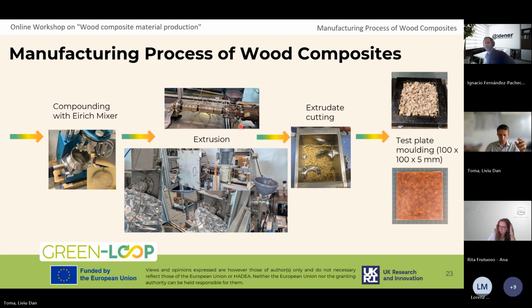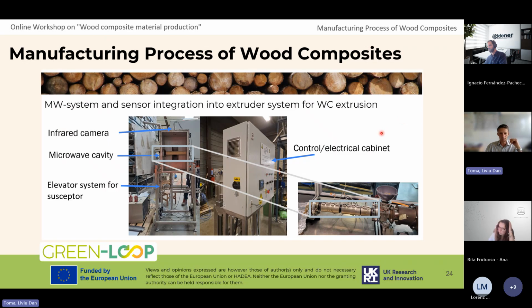The mixtures obtained through the extrusion process were cut, and then with press molding we got test samples in the form of plates, and these were further characterized and machined for special samples for the tribological characterization. As I said, a big part of the work was done with our colleagues in IDENER to integrate a microwave heating system in the extrusion unit. So here is an overview of the unit.